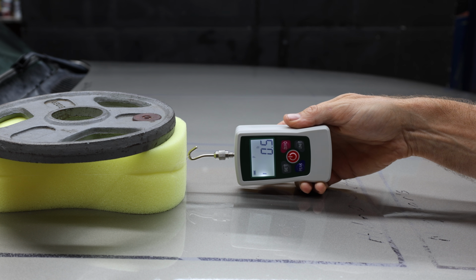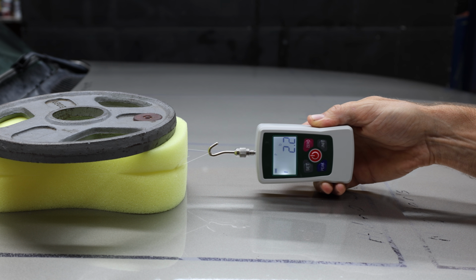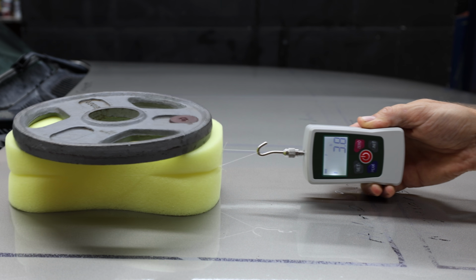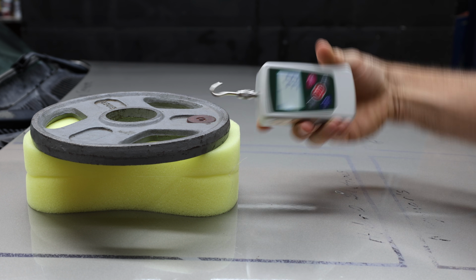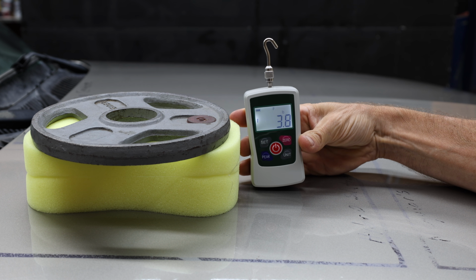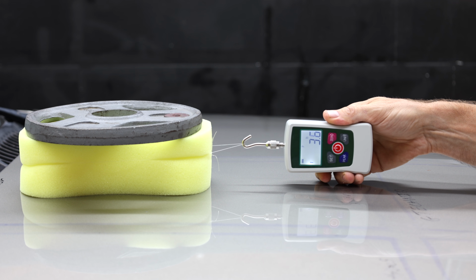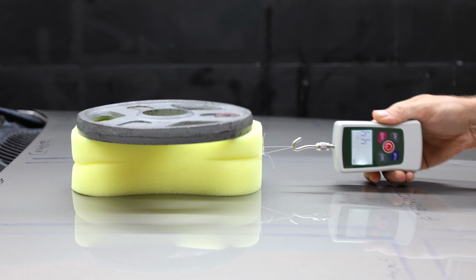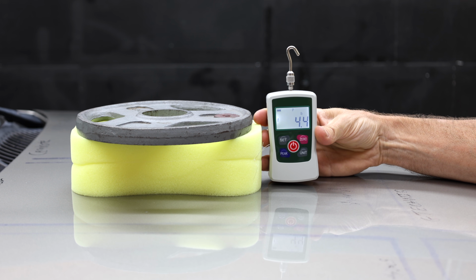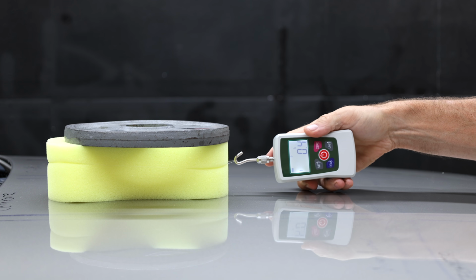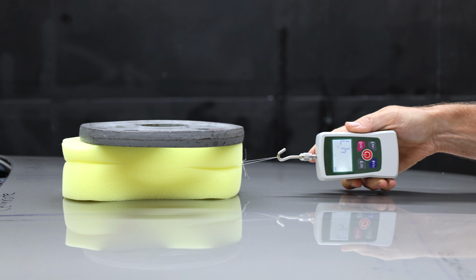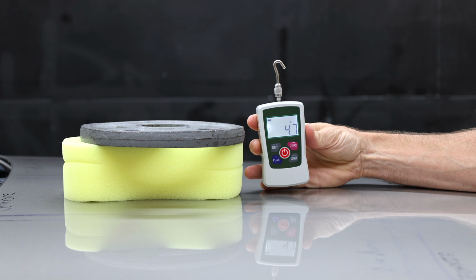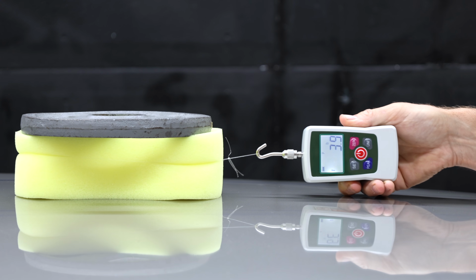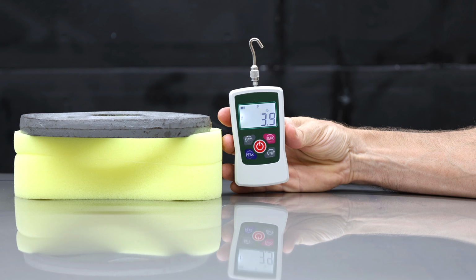We've already tested for hydrophobic qualities, which is the gold standard, but let's go ahead and test for slickness after all of the testing. And the Hybrid Solutions is still outperforming the 4-pound baseline at 3.8 pounds. And the Shine Armor is at 4.4 pounds, which is worse than the baseline. I hope I didn't cause damage to the paint with a degreaser. The CERAKOTE is at 4.7 pounds or 0.9 pounds more than the Hybrid Solutions. The Griot beat the baseline at 3.9 pounds, which is pretty close to the same as the Hybrid Solutions.